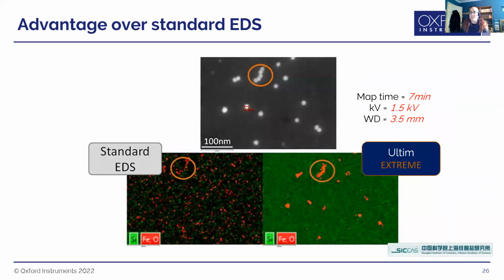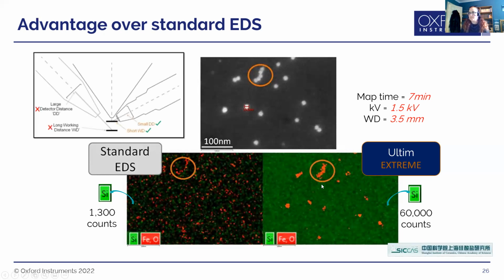And you can see this with standard materials as well. Here we've got some nanoparticles, and this is with a standard EDS, and this is with the Ultim Extreme. So this was acquired within 7 minutes at 1.5 kV with a 3.5 millimeter working distance, so really pushing the resolution there. And what you can see is that the X-ray counts we were receiving with a standard EDS are quite low, but with the Ultim Extreme, it's enormous in comparison, which means we can get better mapping data, better accuracy, and you can see the results here in these images. Again, that's due to the geometry inside the microscope.